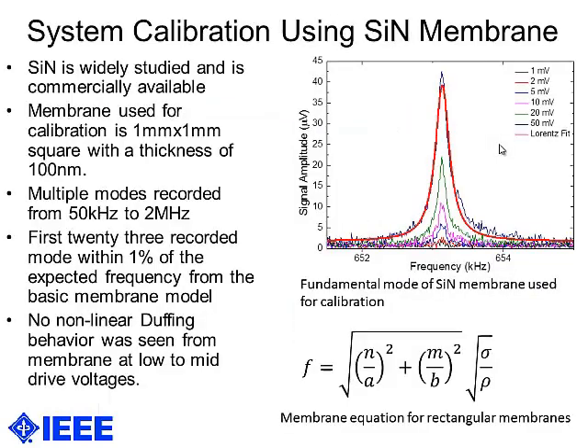We wanted to check our system and make sure that it was calibrated properly. To do this, we used a silicon nitride membrane that is commercially available. The membrane that was used was a square membrane of approximately 1 millimeter by 1 millimeter with a thickness of 100 nanometers. We recorded multiple resonance modes from 50 kilohertz to 2 megahertz and analyzed the first 23 modes in relation to the membrane equation based on square membranes.